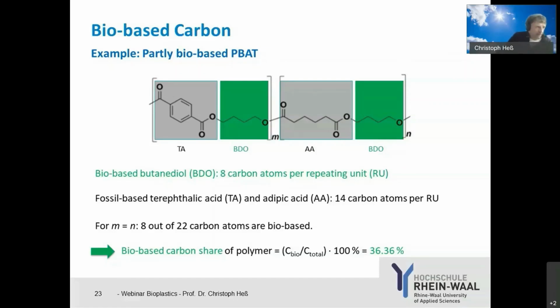Now, if we analyze the bio-based carbon share, we need to count the bio-based carbon in the repeating unit, which is 8: 4 carbon here and 4 carbon here to the right in both butanediol molecules. And then we have another 14 carbons that are fossil based, coming from terephthalic acid and adipic acid. This is on the precondition that m is equal to n, so that we have the same number of aromatic and aliphatic acid molecules in the polymer structure. So in total we have 8 plus 14, which is 22 carbon atoms in the entire repeating unit, of which 8 are bio-based.